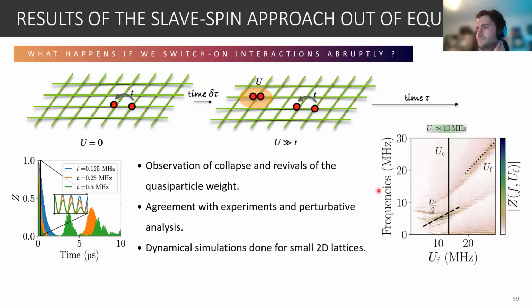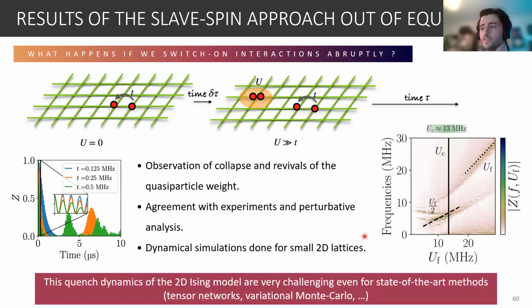This is something that is observed in the literature, and which is quite well explained with the physics of the Fermi-Hubbard model. So we are happy because we can recover the physics of the out of equilibrium of the Fermi-Hubbard model with this method. And the quench dynamics is very challenging for state-of-the-art methods, for instance, for tensor networks or variational Monte Carlo, because of entanglement and entropy, which is growing through time. So now the question is, are we able to go further than classical simulation?